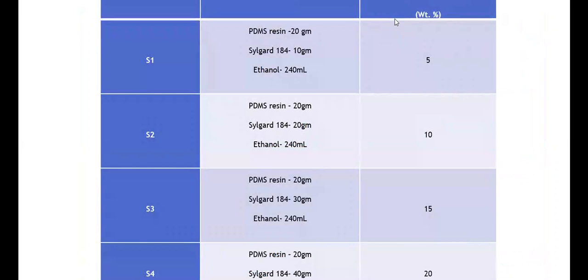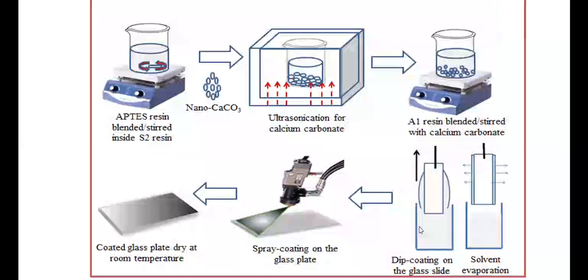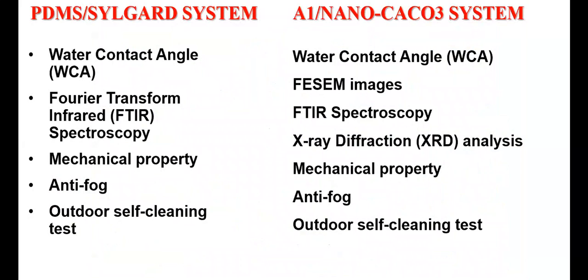So these are the formulations of our PDMS and Sylgard. We fix the PDMS ratio, but we increase the weight ratio of the Sylgard, and we find what is the best property out of it. After we do the coating, the PDMS Sylgard system, we do water contact angle measurement to see the hydrophobicity of the coating system, and the cross-linking ability by using Fourier transform infrared spectroscopy. We also test mechanical properties, anti-fog properties, and outdoor self-cleaning.